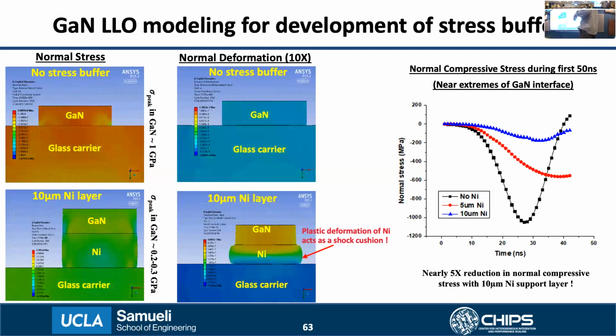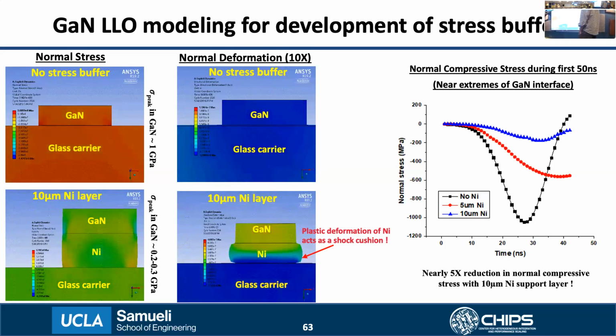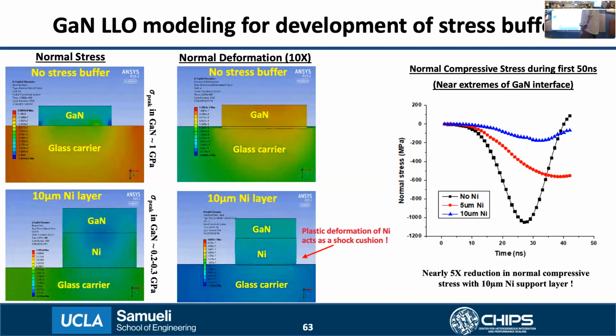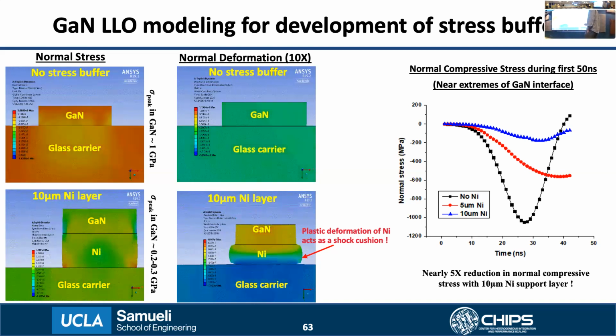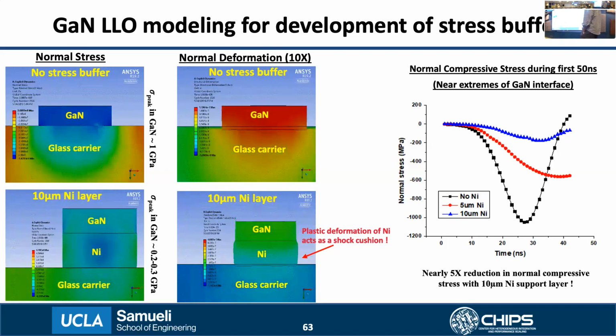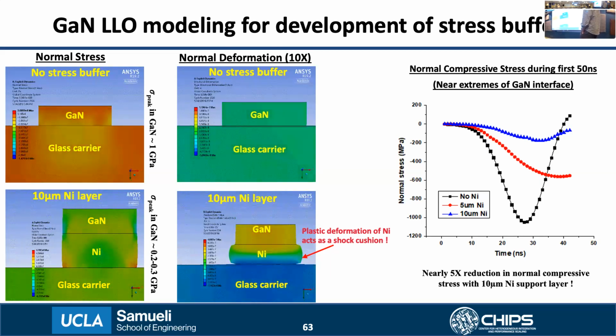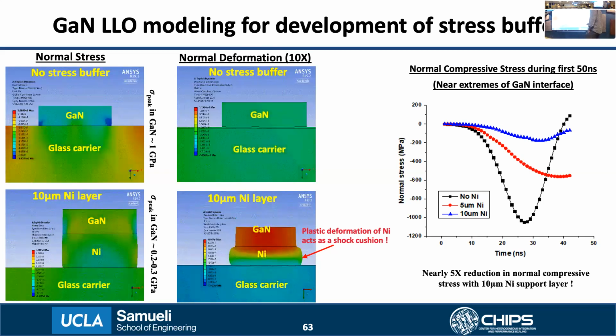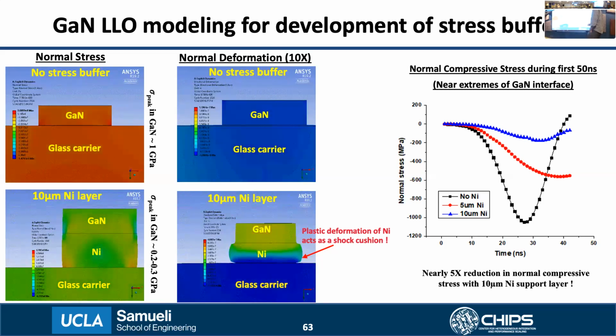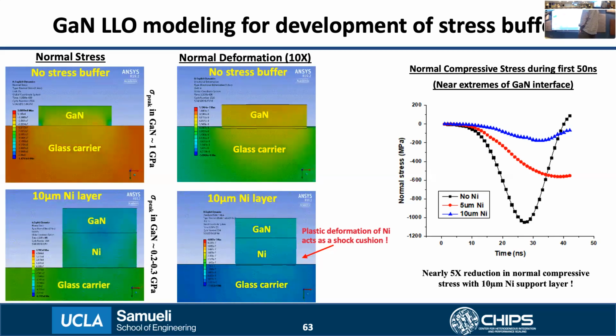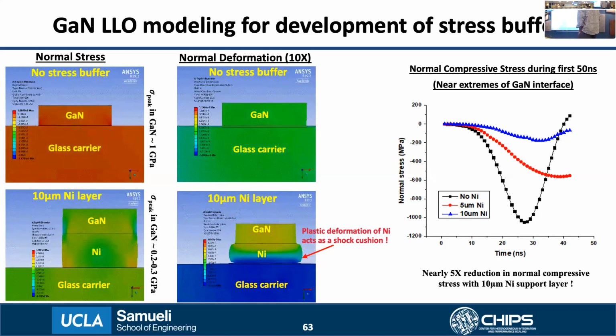If you see the animation in the bottom right, which is the normal deformation when the nickel is used, you can clearly see how this process actually works. When the incident pressure shock wave hits, the nickel plastically deforms and acts as a cushion for the incoming shock wave, which in turn reduces the peak stress within the GaN, because the stress wave is essentially dissipated in the nickel itself. This is the reason why the peak stress within the GaN is significantly reduced when we use this nickel stress buffer layer.